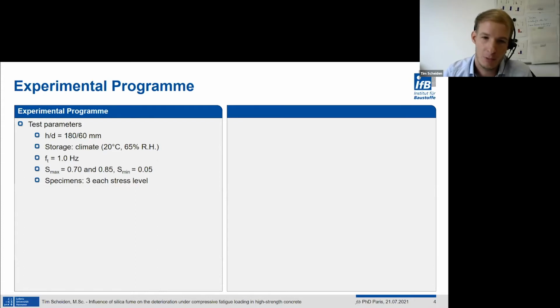To investigate the influence of the silica fume, systematic tests with cylindrical specimens with a height of 180 millimeters and a diameter of 60 millimeters were conducted. Our specimens were stored in climate chamber conditions with constant temperature and relative humidity. The sinusoidal load frequency is set to a constant 1 Hertz with a maximum stress level of 70 or 85% and a constant minimum stress level of 5% of the reference strength.